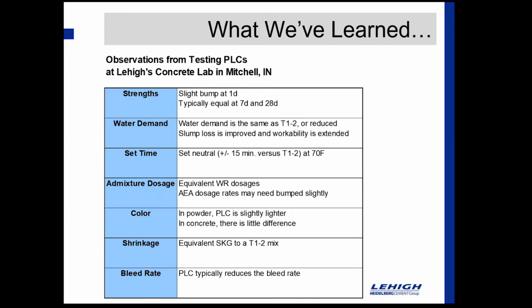Color, if you look at PLC under glass with that plant's equivalent type 1 or type 1-2, the PLC is going to be a bit lighter. You've got about 6% more limestone in that cement. And in terms of concrete, though, once you put that with that concrete sand, it kind of washes that color difference out, and there's really not very much difference at all.